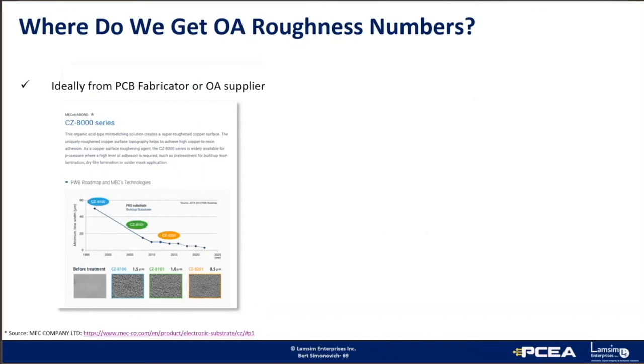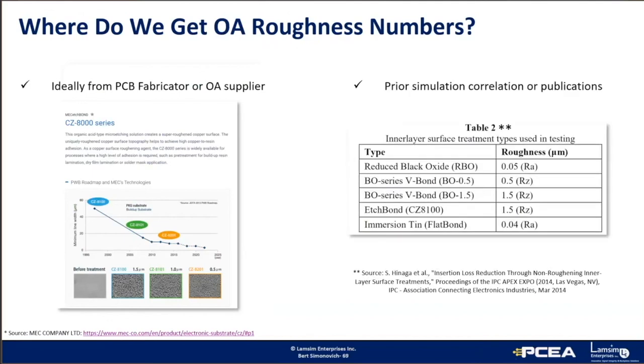Similarly, you can get the oxide alternative roughness numbers from the supplier's data sheets, but they're not as easy to find. Failing that, you can get them from prior simulation correlation, or even from past publications, or perhaps even from your fab shop if they share that information. Here's an example of innerlayer surface treatment study done by Scott Hanaga back in 2014, which lines up well with the CZ8100 in the data sheet.